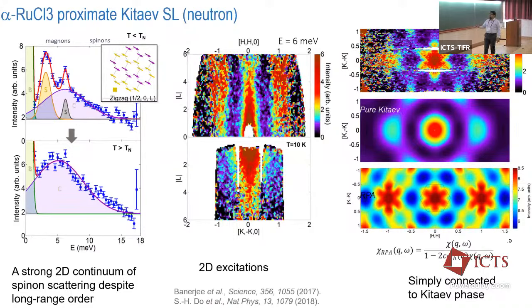If you look at the in-plane scattering, essentially, if you squint your eyes, you can see a star here, a star here, a star here. It starts to match the pure Kitaev calculation. Not quite, at low energies, basically. What we find is that you can do a very simple RPA. In fact, Johannes Knolle, sitting here, you can do a very simple RPA. And then you can think that, OK, you're starting to see what the spectrum looks like. So you might be simply connected to the Kitaev phase.